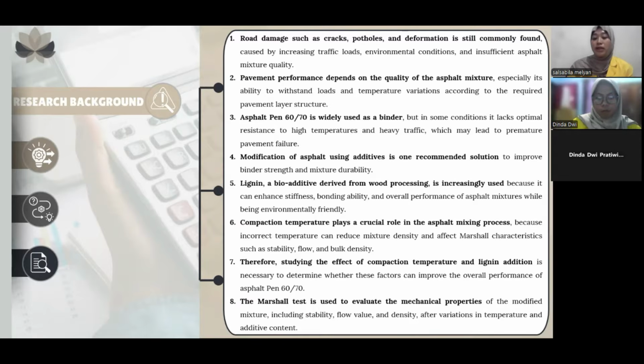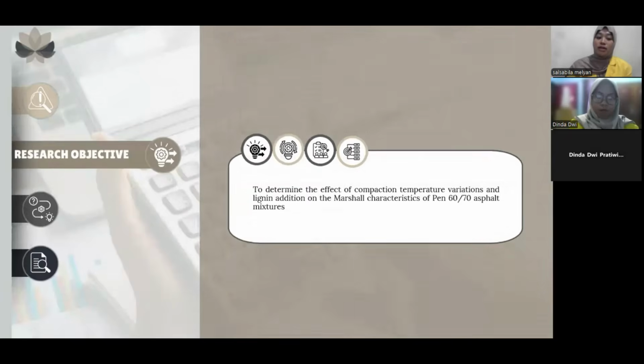Compaction temperature is very important. Wrong temperature can reduce the quality of asphalt mix. The Marshall test helps us check the mechanical properties of the modified mix. Continuing from the previous background, the research objective is to determine the effect of compaction temperature variance and lignin addition on the Marshall characteristic of Pen 60/70 asphalt mixture.